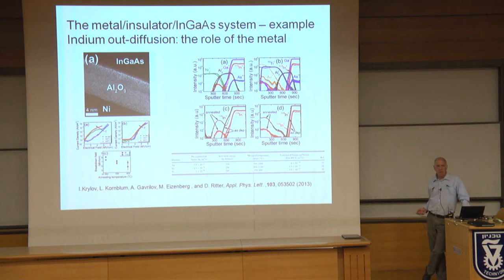There are several things that Igor has discovered. Here I'm just pointing out one of the topics. It's the out-diffusion of indium from indium gallium arsenide into the aluminum oxide. Igor actually discovered this. Now many groups have seen it and are working on this problem and trying to see what kind of trouble the indium atoms, which are diffusing into the alumina, cause and how this can be eliminated. Igor actually showed that nickel here is a sink for indium atoms and can solve some of the problem by absorbing most of the indium coming out from the indium gallium arsenide into the alumina.